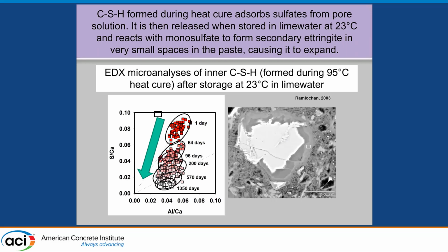And then what happens afterwards is you put the concrete in, or the mortar bar, in this case, in water, and you get leaching. And so the sulfate starts to come out. So it starts at 1 day, you get these high sulfate ratios, and then at 64 days, 96, going down to several years here, the sulfur is coming out of the CSH. So that's what all these dots are. It's the sulfur levels within the CSH itself.